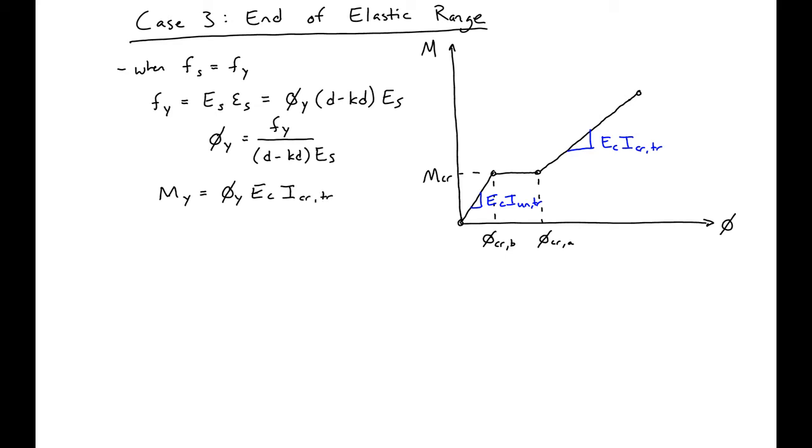The other point that may be a concern is the point when our concrete goes inelastic, so when our concrete stress is equal to 0.7f'c. At this point,